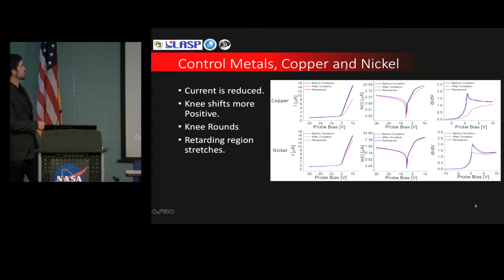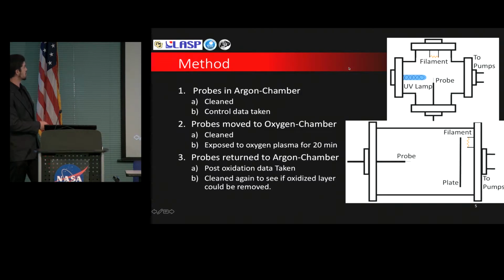Black and blue are, oh, I'm sorry, one other thing. While the probes were in the argon chamber, after the control sweep was taken, they were cleaned by the same in situ methods as they were at the beginning to see whether or not this oxidized layer could be removed. This was done for two reasons. One, to see whether or not this layer could be removed by a spacecraft. Additionally, it was to make sure that we had indeed recreated the exact same plasma environment and that the change wasn't due to a change in the plasma rather than oxidation.